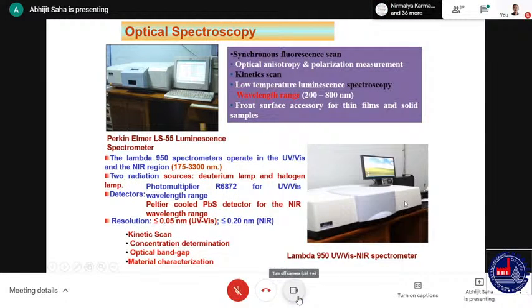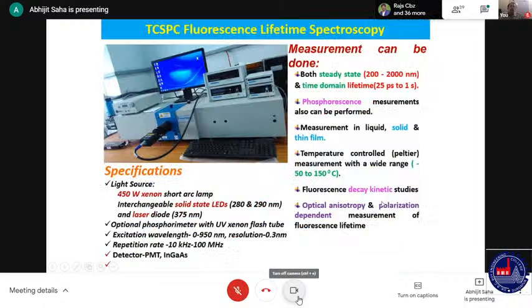Our facilities, particularly in the chemistry lab, include the fluorimeter, the fluorescence spectrophotometer. We have the UV-NIR spectrometer, whose range is very high, 175 nanometers to more than 2000, I think around 3000 nanometers. So it is a long range we can cover. We have a lifetime measurement setup using the time-correlated single photon counting (TCSPC) system, and this is a combined system. Basically, you can measure the static fluorescence as well as lifetime measurements. Both can be done, and it can be done from 25 picoseconds to 1 second. It also has emission, and we can measure in the ultraviolet, visible, and NIR range also. So this is a very versatile system we have here.